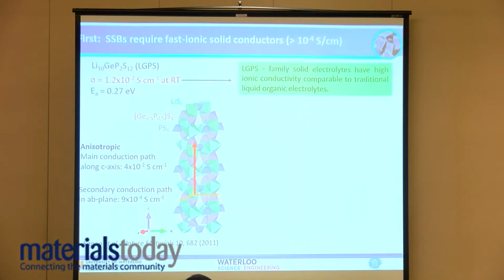I'll just tell you a little bit about some solid-state sulfides which have been developed. So the first requirement is that you have a good fast ion conductor. Before you even worry about nano-sizing it, you need to have a good material. And that means it has to have a conductivity in excess of 10 to the minus 4 Siemens per centimeter, because that's limited by the size, the thickness of the electrolyte that you can sustain in the cell.